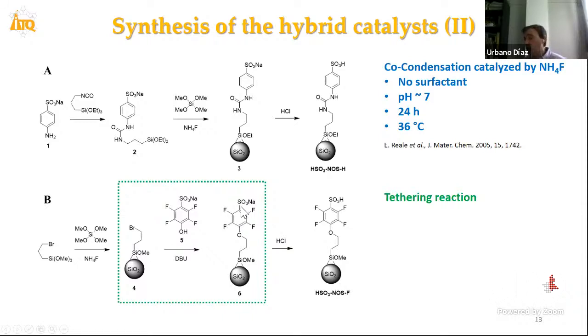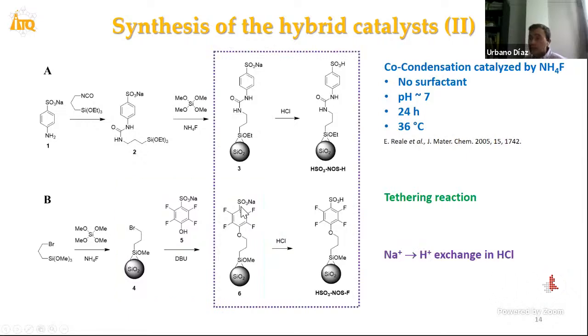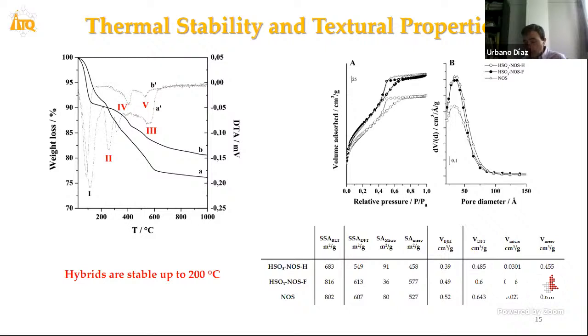Finally, the exchange process to exchange the sodium cations by protonic forms, this process to obtain the final pendant and accessible sulfonic groups in the surface.